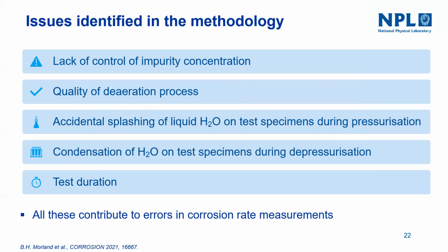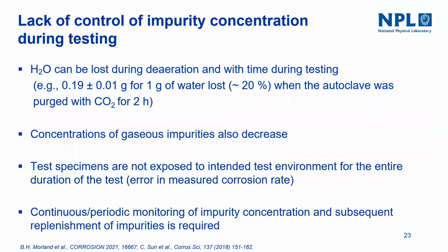And the degradation of the autoclave. Morland et al. have identified other issues like accidental splashing of water on specimens, condensation of water during depressurization, and actual test duration. So all these factors contribute to the errors in corrosion rate measurements, which I'll be going through. So one is H2O content.